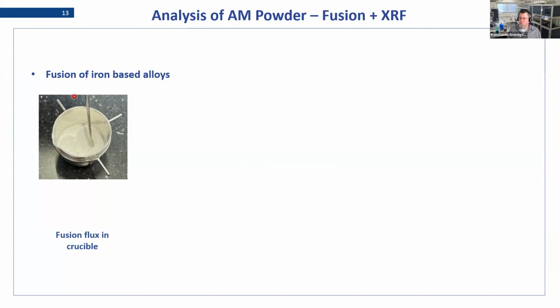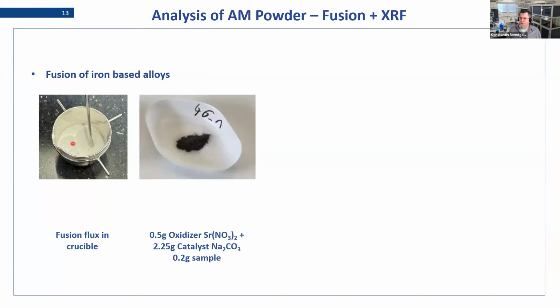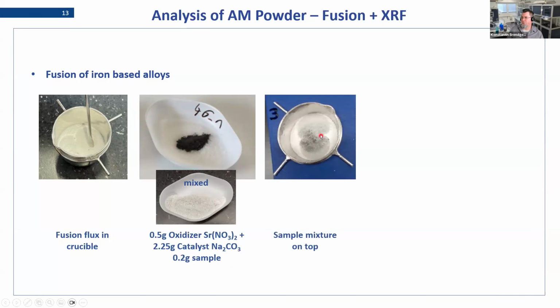So we put the fusion flux in a crucible, and usually we make a little dent in the middle. In an extra little container, which we call ships in Germany, is where we mix our sample with the oxidizer. In this case, that was strontium nitrate, and we used sodium carbonate as a catalyzer. And then the sample on top. We mix this in the little ship, and then this gets transferred on top. We don't mix it here in the crucible in order to prevent the sample from touching the platinum and causing more wear and tear than we need.